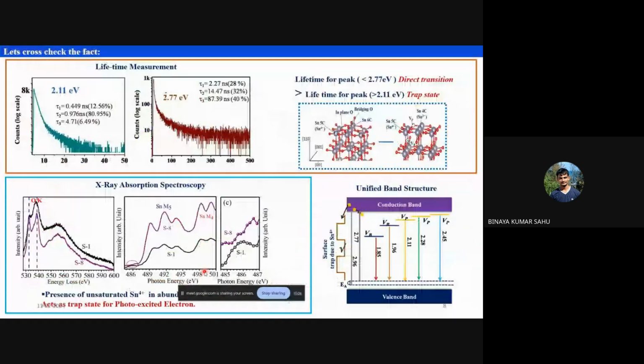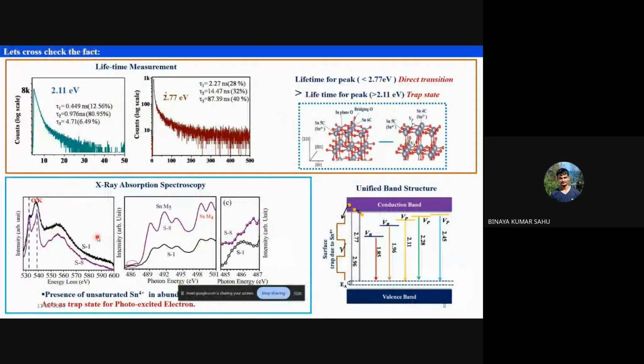So we carried out a similar experiment. This is the lifetime measurement. And what we saw, this 2.77, as I told, is the transition related to the surface defect. They show a higher lifetime. The lifetime was around 87.3, or nearly 90 nanoseconds, whereas for the bulk defect, it is around 4.7 nanoseconds. So that's why I was asking you to kindly remember two particular things. First one is lifetime: because it is related to the surface defect, it is 2.77, then the lifetime is high. So whatever they have assumed or proposed, they were exactly correct.